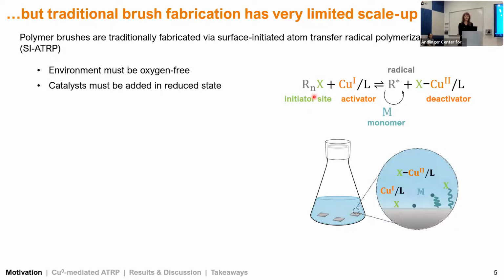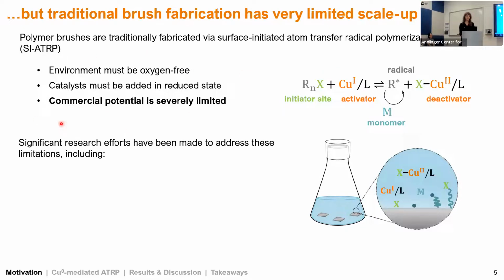We also have to add our catalyst in the reduced state, so not exposing it to oxygen prior to addition. And these factors severely limit potential for commercial scale up because it's hard to achieve this other than in a very controlled lab environment. So there's been significant efforts to address this, including adding reducing agents to the reaction solution.